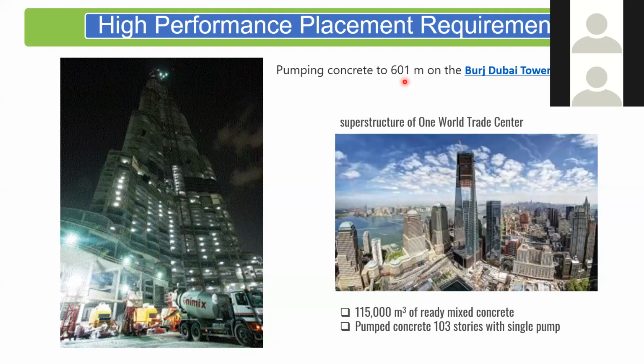So technology development did take place. In fact, Samsung, the company that took up the challenge of pumping concrete, developed special pumping systems that would allow concrete to be lifted to a head of 600 meters and above. But more importantly, now I have to make sure this concrete that I'm going to put in a pipe and pump should be able to withstand the pressure, should remain homogeneous. That means it should not start segregating and separating out under pressure. And when it comes out of the nozzle at the other end, it should remain as one cohesive material and fill the form. So that is the requirement from concrete, and that is now being specified as a performance requirement from fresh concrete.